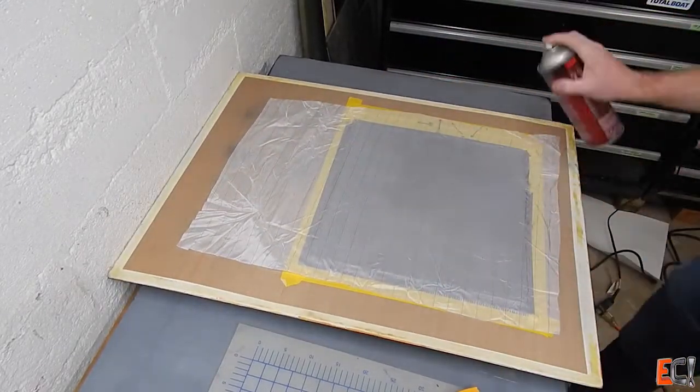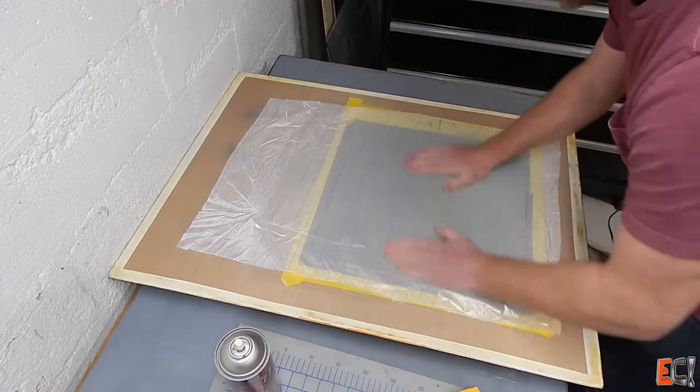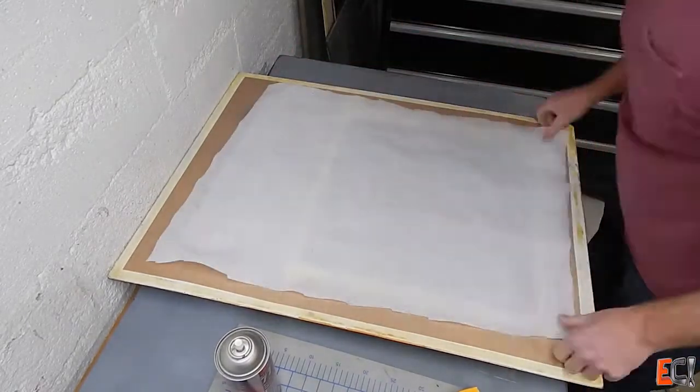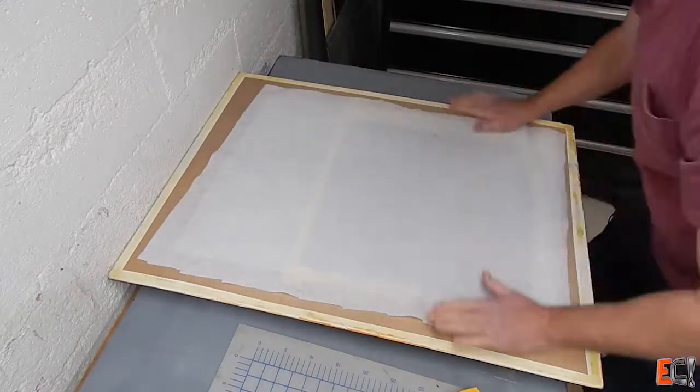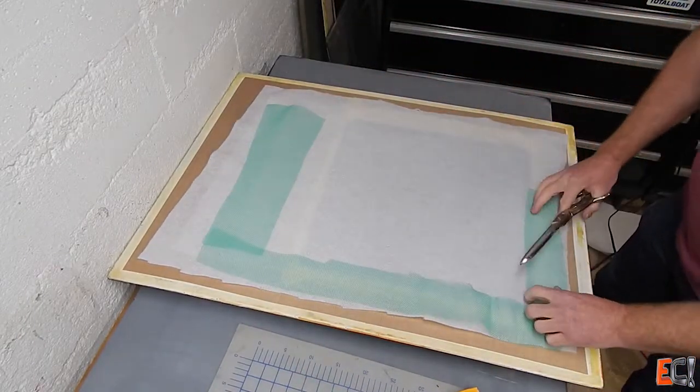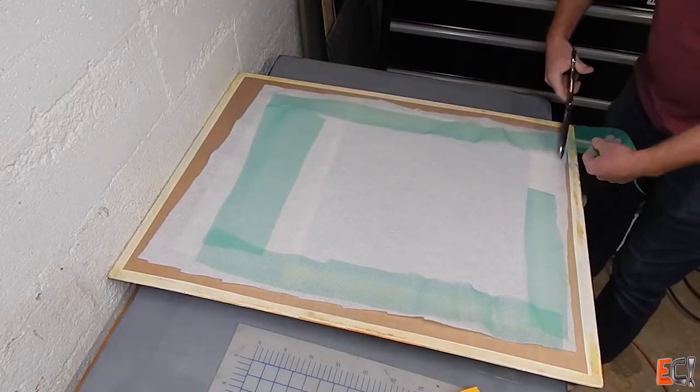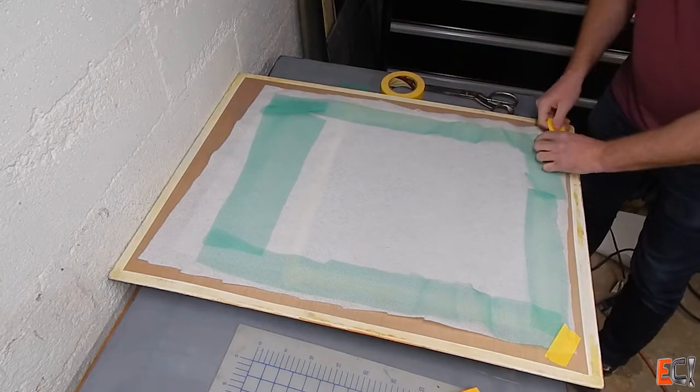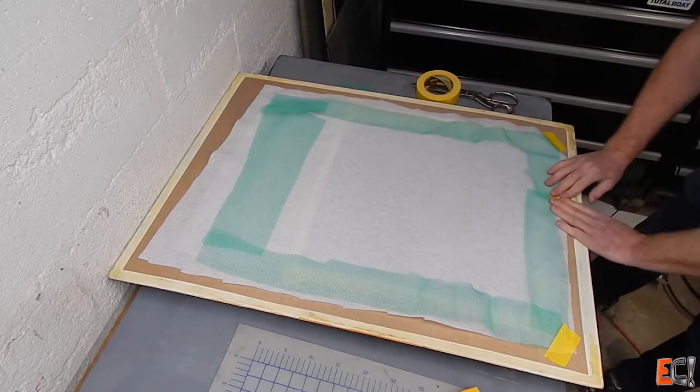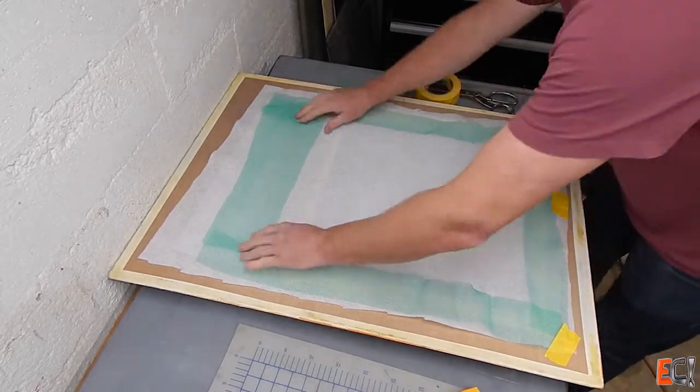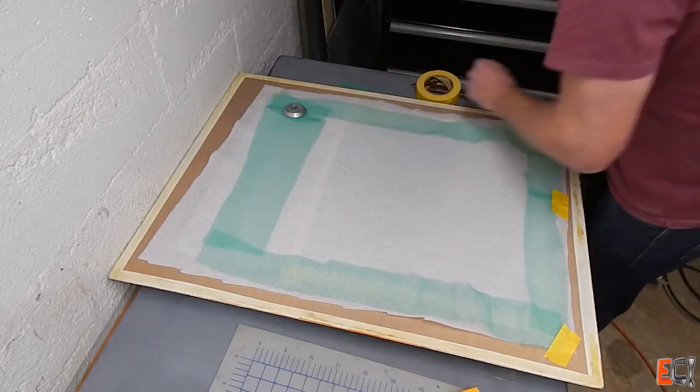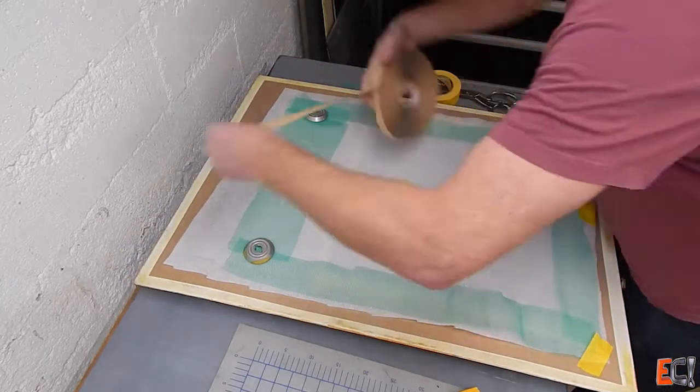Here not worrying about it too much. Again the thicker laminate the less the bleed stack is a concern because the fraction that you're bleeding off is reduced. I'm putting some breather and this green mesh around the perimeter so they won't pull too much resin out but will still distribute vacuum all around. We'll see how much bleed I get depends on the cook.